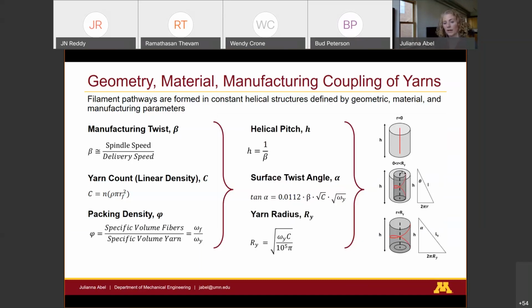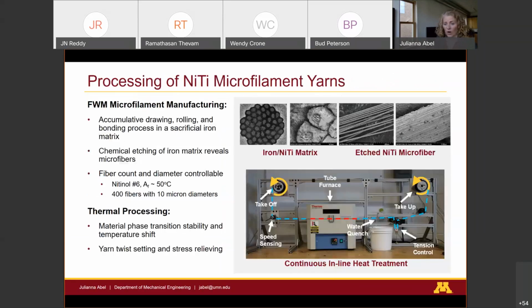And also, because we're applying twist, we have different fibers in different regions. So we have the center fiber that's straight, that's acting as just a linear actuator, and then we have these torsional or helically twisted fibers around the outer edge. So we have a really complex interior stress profile, and we're trying to understand that relationship of where we are in the structure, how we apply twist to get a desired macroscopic performance.